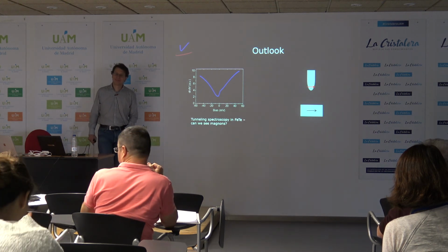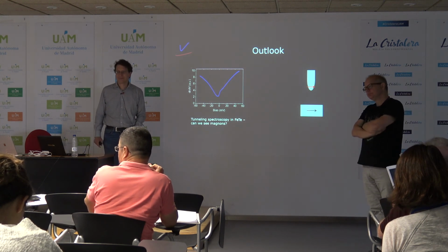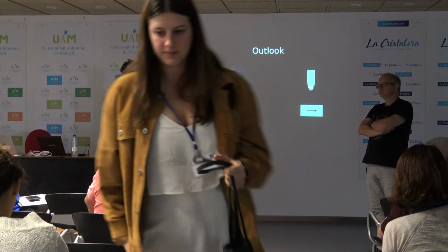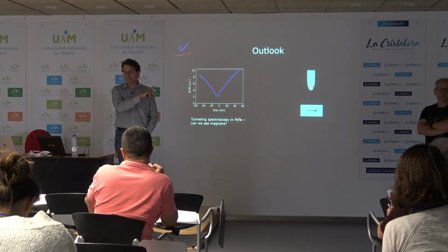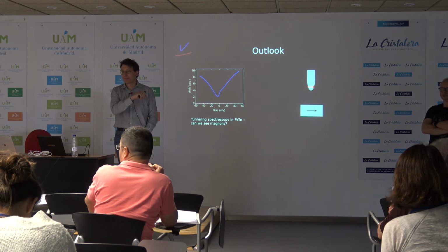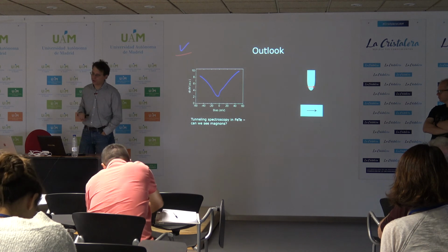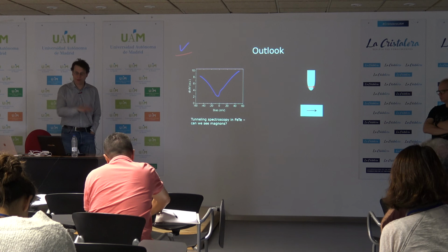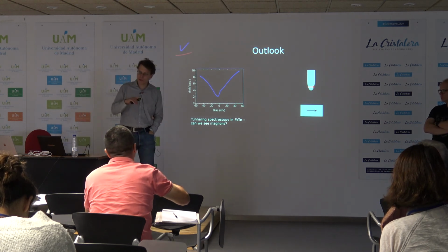So when you use the spin-polarized tip and change the magnetic field, does the direction of the moment of the tip also change or not? Normally it's fixed, because if it's not fixed, then the comparison with different fields becomes complicated. In iron tellurium, we are fairly certain that only the tip follows, not the sample. So we deliberately make a ferromagnetic tip, so that the tip follows, but the sample does not.